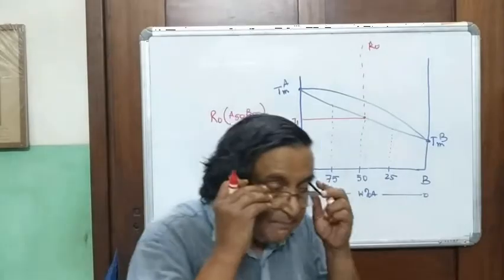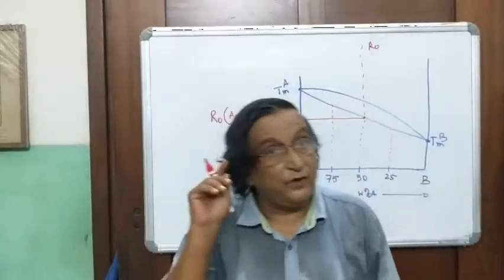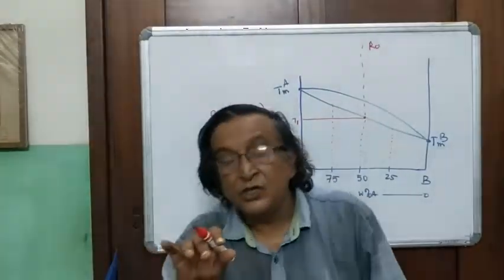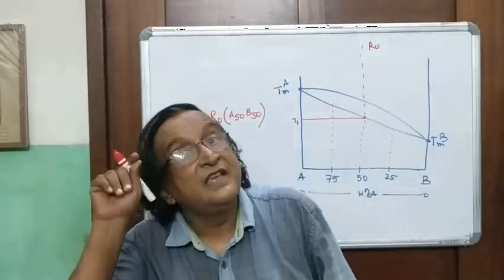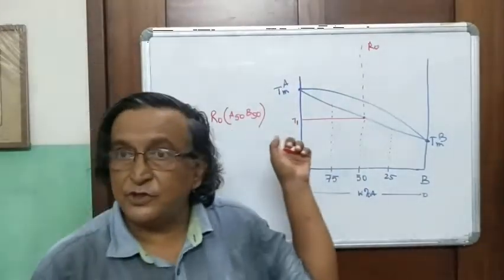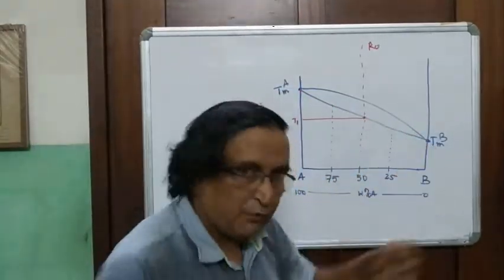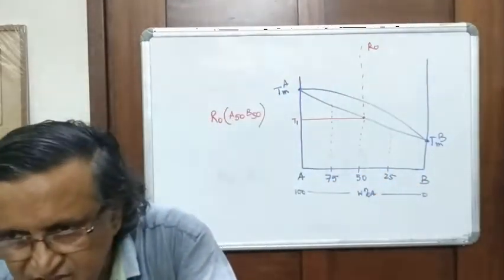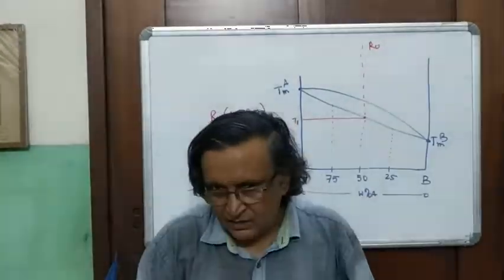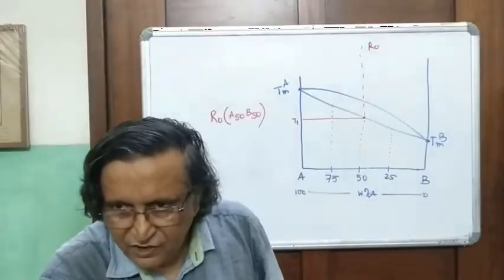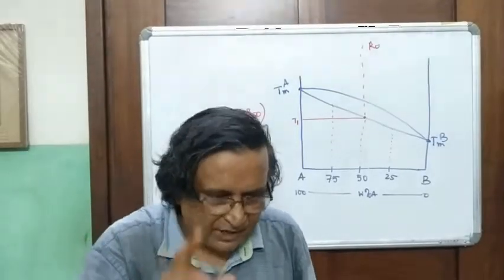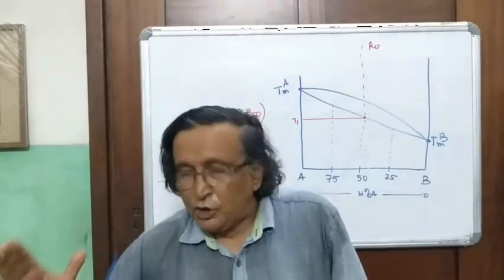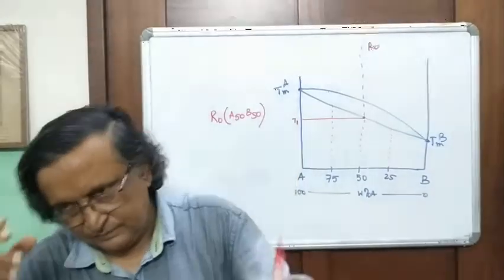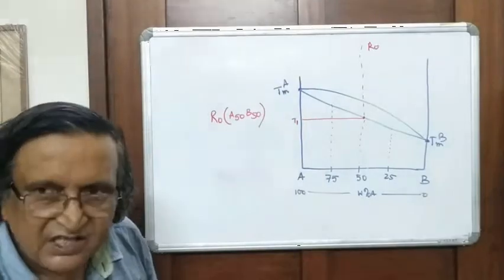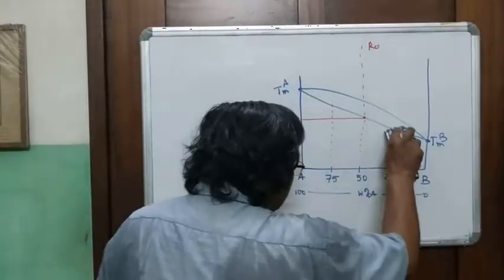This is a major difference from the simple eutectic system. If you remember, in the simple eutectic system, no matter what you heat, the first melting temperature remains the same. Remember, it's the eutectic temperature. But here, there is no eutectic temperature. If you melt a mineral, the melting would be initiated at a temperature depending upon the composition of A and B in the mineral. But in the eutectic system, the proportion of A and B does not dictate the temperature of melting at low degrees of melting. There it was always the eutectic temperature, no matter what proportion of A and B you took. So long as A and B were there, the melting temperature was fixed. But this is not valid if you have mineral composition. So I will erase this at the moment.